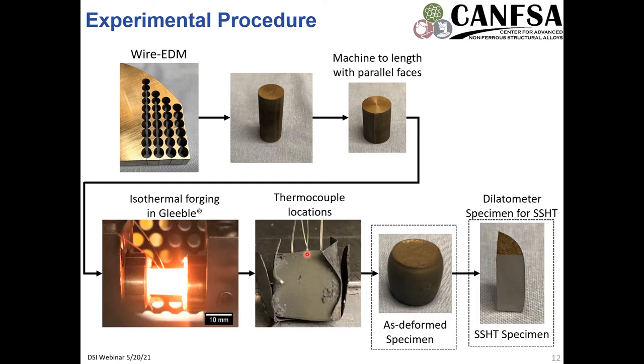We spent a fair amount of time on process development in the Gleeble to try to reduce the thermal gradients. We were fairly successful in this. Initial thermal gradients were quite large, and this material is extremely sensitive to temperature deviations. We're operating nominally at about 1100 to 1120 Celsius, and so a 10, 20, 30 Celsius thermal gradient causes a drastic change in the mechanical and microstructural response. So we took a lot of time to do process development to get this consistent and reliable. Afterward, we took the specimen and sectioned it into usually six different axially symmetric specimens to do different heat treatments upon the material, as well as look at it before and after the supersolvus heat treatment.